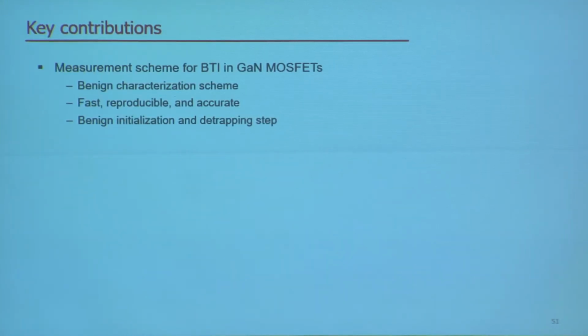So with that, I will summarize our key contribution of this work. What we did was first we developed a measurement scheme to characterize BTI in gallium nitride MOSFETs. There's a benign characterization scheme that we calibrated that does not contribute further to the device degradation, which offers fast, reproducible, and accurate measurements. We have also calibrated a benign initialization and reset step, which is the thermal detrapping step, to help us speed up the recovery process, and also distinguish the recoverable phenomenon from the permanent degradation.